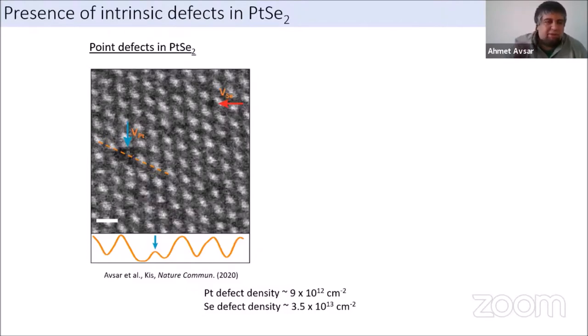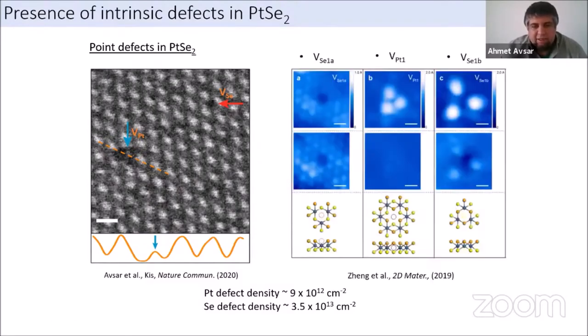And we don't grow these materials in our lab, so we were getting them from a manufacturer. But the question was, are there this type of defects in these materials? And we had TEM studies, and indeed, we have a high concentration of this type of defects in the material. And also, there was another study done through STM, scanning tunneling microscopy, and it was shown that indeed these platinum vacancies exist in this material, in the same type of material grown as in our study.